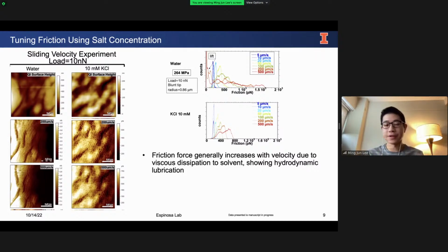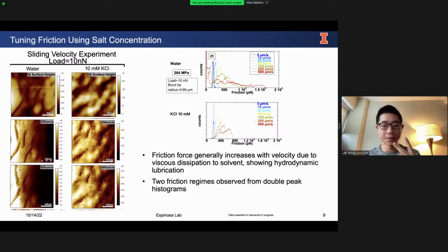And I believe this is due to just viscous dissipation to the solvent. The faster you slide, the more energy you lose to the solvent. And it's a feature of hydrodynamic lubrication. What's more interesting is that I'm seeing two friction regimes coming out from my friction maps.